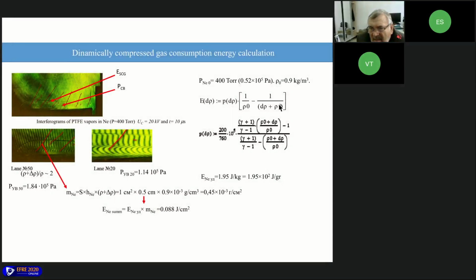And taking in mind that some energy absorbed in the compressed gas is kinetic energy and inner energy, if we look at the interferograms, we can estimate the energy in the plasma layer. The ratio of height between the shock wave and the target, and the contact boundary and the target, allows us to estimate that the density ratio is about 2.